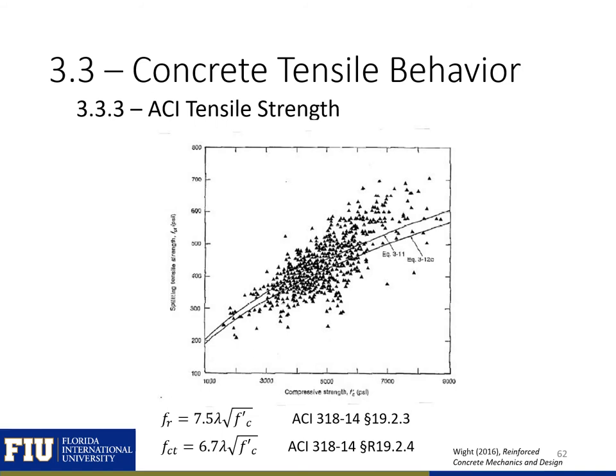Shown here are the experimental results for many different split cylinder tests. The splitting tensile strength is plotted versus the compression strength for each test. There's a large amount of scatter in the data because the tensile strength of concrete has a lot of variability. The only specified tensile strength in the 318 building code is the modulus of rupture strength, which is taken as 7.5 times lambda times the square root of f'c, where lambda accounts for the effects of lightweight concrete. The commentary also mentions another relationship for the splitting tensile strength, which is 6.7 times lambda times the square root of f'c. Both of these expressions more or less split the scatter of data in half.